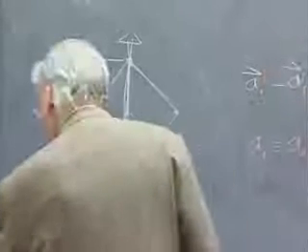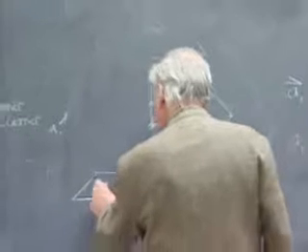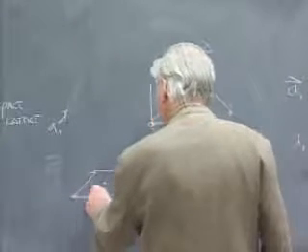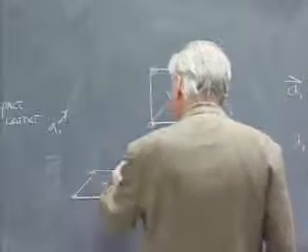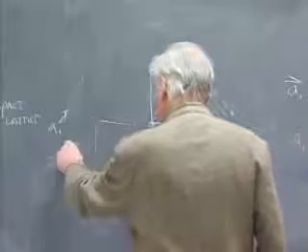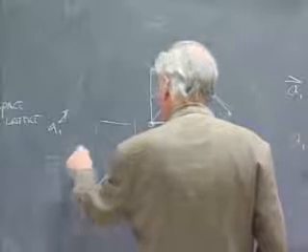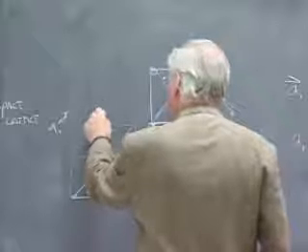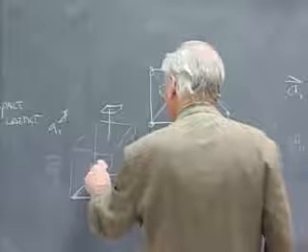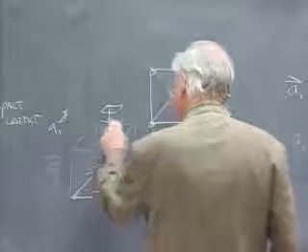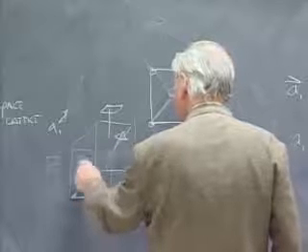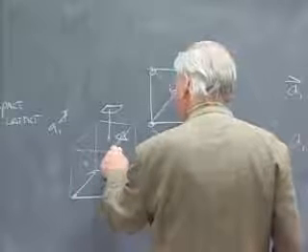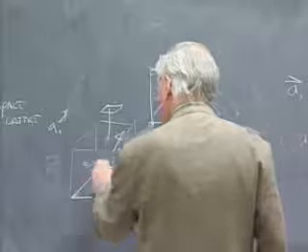So what I have now is a cell that is centered, has a centered net in the base, and has translations that are perpendicular to the base like this. And if this is the direction of the fourfold axis, and this is the direction of the threefold axis, that threefold axis is going to put a centered lattice point on the remaining